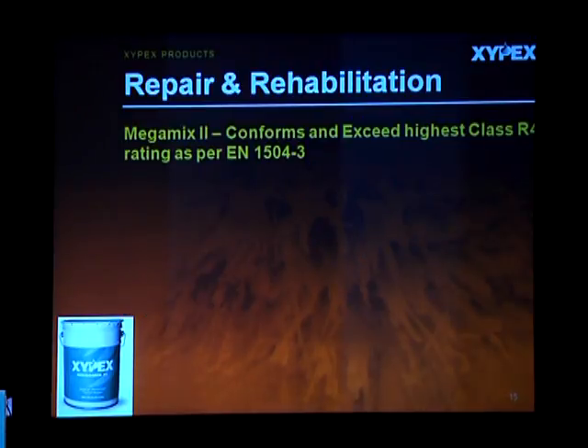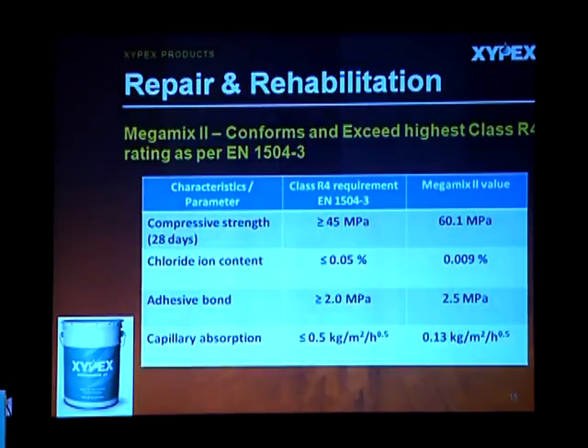There are several studies conducted on this particular material. We do not have a very comprehensive IS code to test this material, but we have a very popular internationally approved EN 1504 code which evaluates high strength repair material on different parameters. There are 15 different parameters. I've just highlighted 4 of them, which include compressive strength, chloride ion content, adhesive bond and capillary absorption. And you can see in almost all the parameters, this material meets or exceeds those benchmarks.